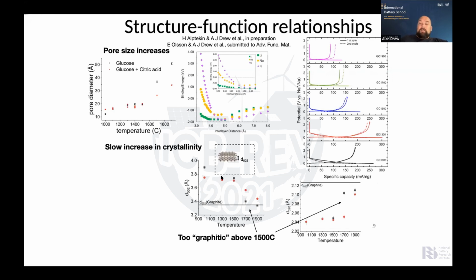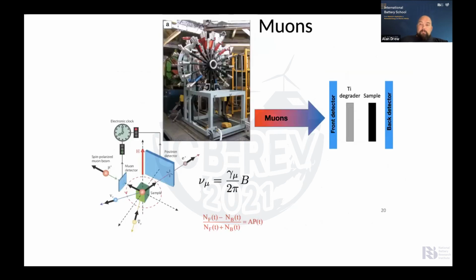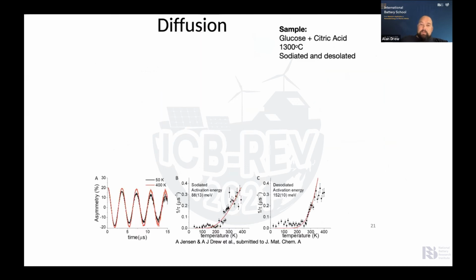Okay, so the highest capacity here corresponds to the optimum position of the pore size and the O2 distance and the O2O distance. You need to get all of these optimized, which you can do with temperature. So GC 1300 appears to be the most appropriate annealing temperature. All right, just quickly, because I'm running out of time.